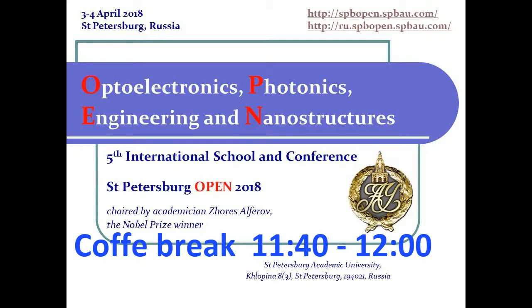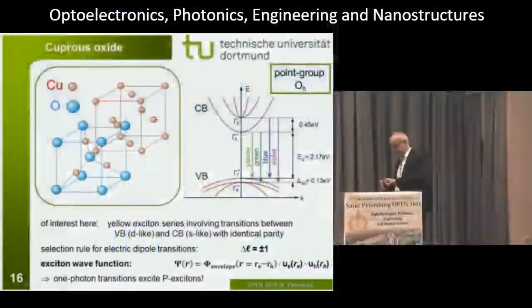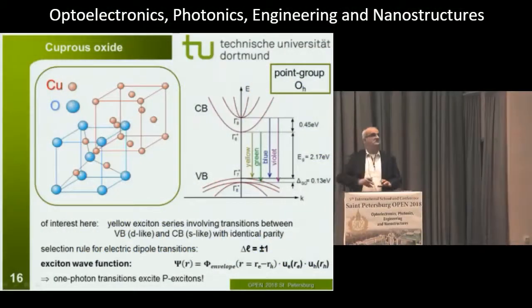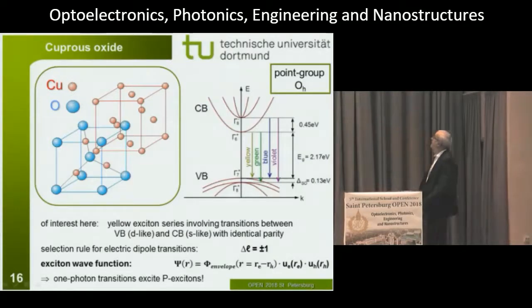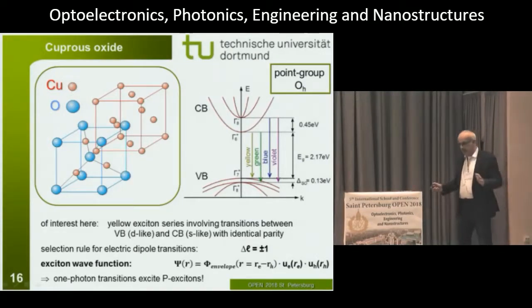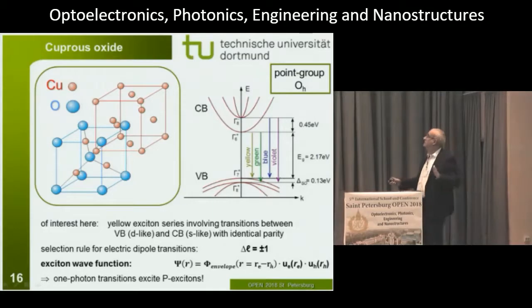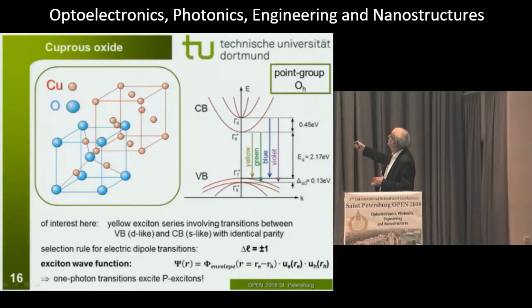Very briefly, we have a BCC lattice of oxygen atoms and an FCC lattice of copper atoms, and they are shifted by a quarter of a space diagonal relative to each other. Simply speaking, it's the simplest case of a two-band semiconductor. So you have here your conduction band, it has even symmetry, you have your highest valence band, it's also a single band, and we are interested in the excitons involving the lowest conduction band and the highest valence band, and these excitons form the so-called yellow exciton series, just for historical reasons.